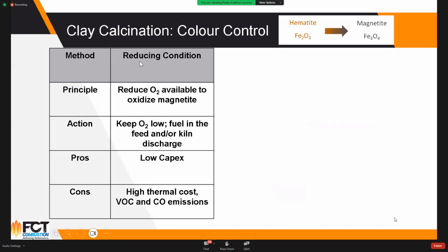One of the first of the traditional methods is to promote a reducing condition. You reduce the oxygen available to oxidize magnetite, or you keep the oxygen low. It can be fuel in the feed, or it can be fuel in the kiln discharge. The good thing about using those methods is that it's relatively low in capex, but the con is that probably all the fuel you're putting in the feed is going to be lost. So you increase the overall heat consumption. You might also be facing an increase in VOC and CO emissions. So it's cheap to be installed, but probably you're going to pay an important fee for running with this configuration.